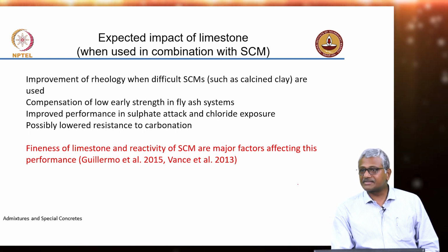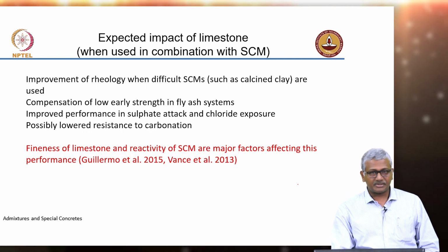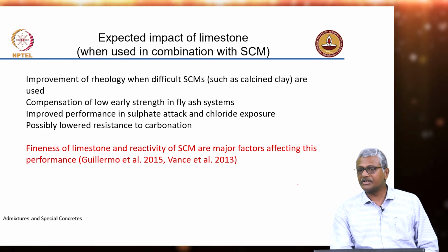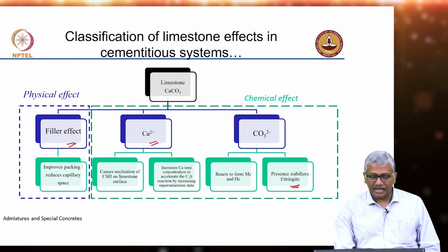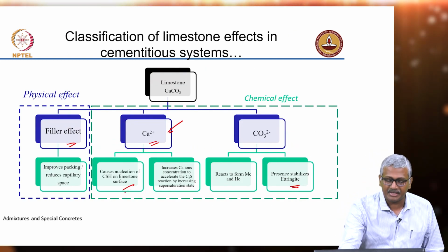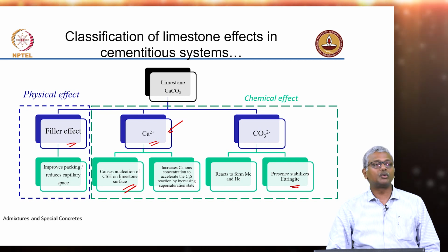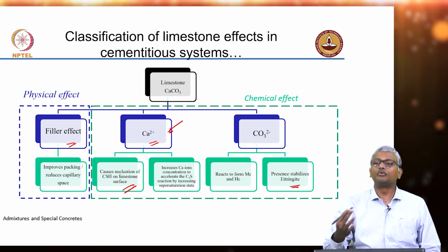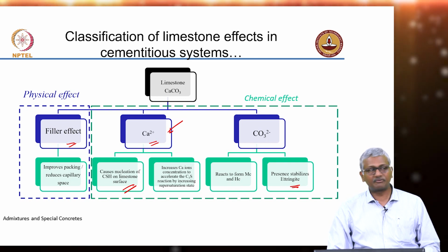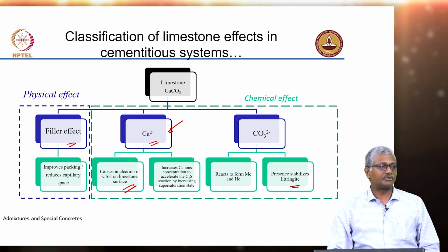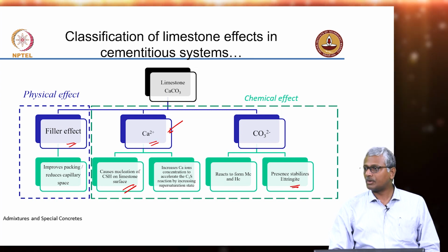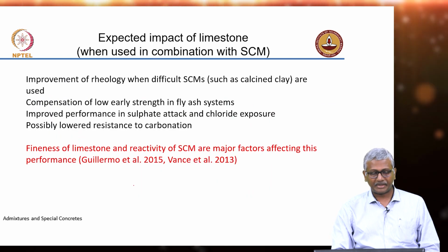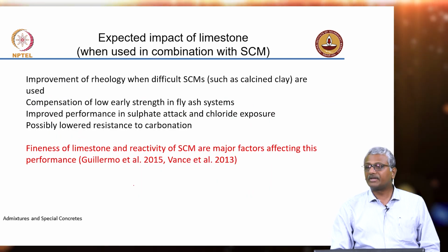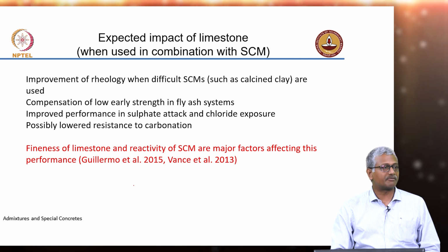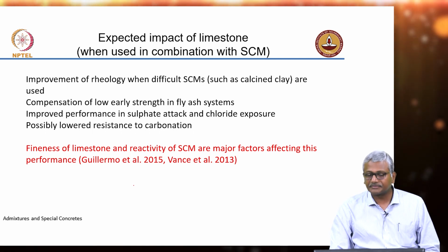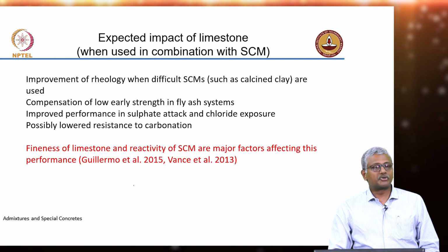Okay. In fly ash systems, when early strength is compromised because of the slow reaction of fly ash, the fact that your limestone can provide this increased C3S hydration by causing nucleation of CSH will improve the early age strength also. So with fly ash, you can offset some of the early strength problems that you have with fly ash. And generally, we can expect that there is going to be an improved performance in sulfate attack because ettringite is stable, and in chloride exposure. Why?